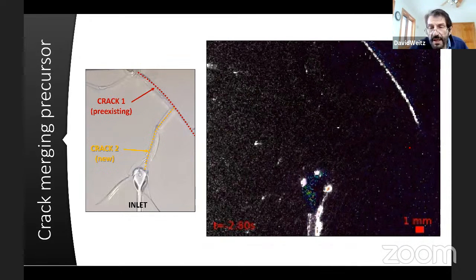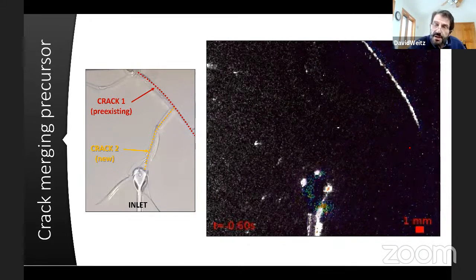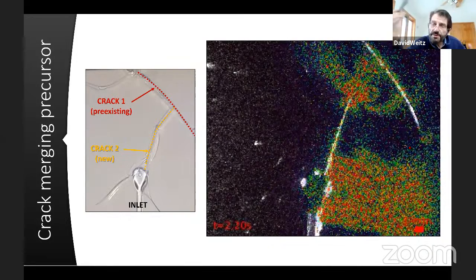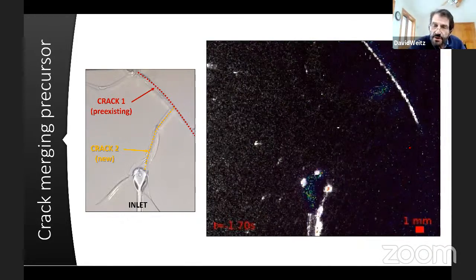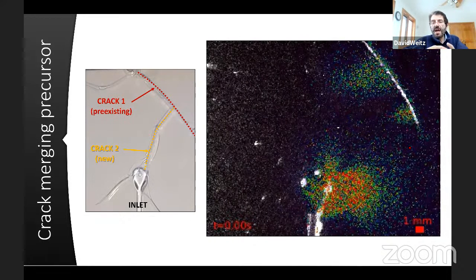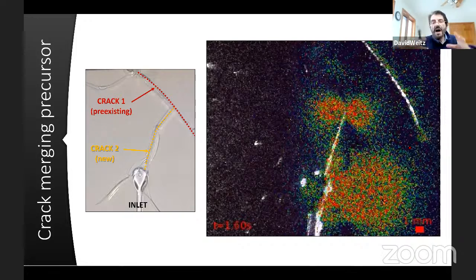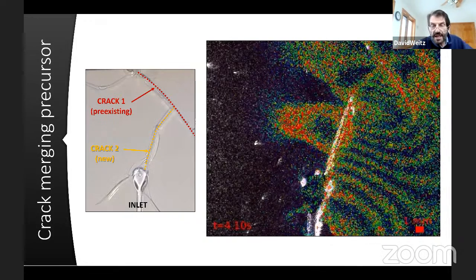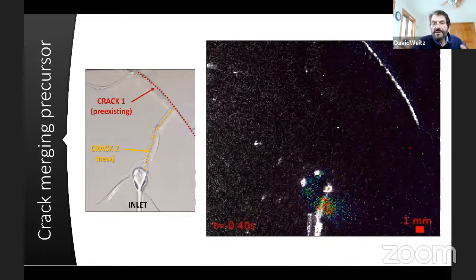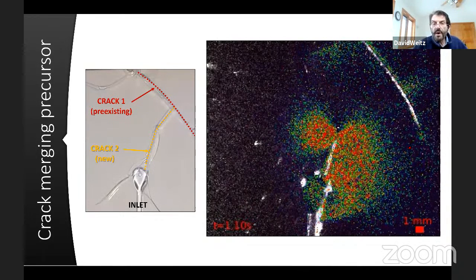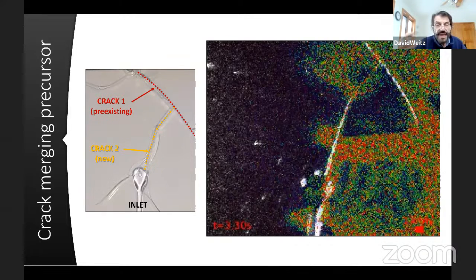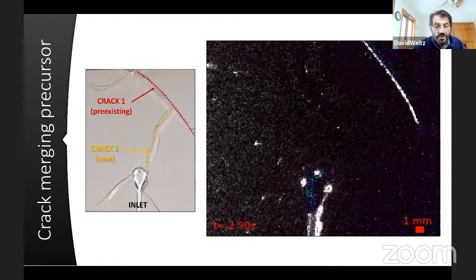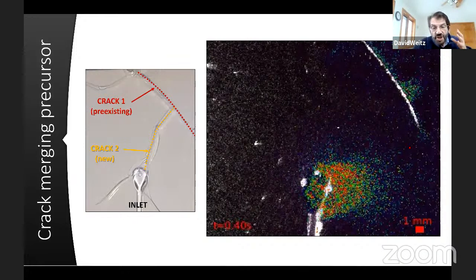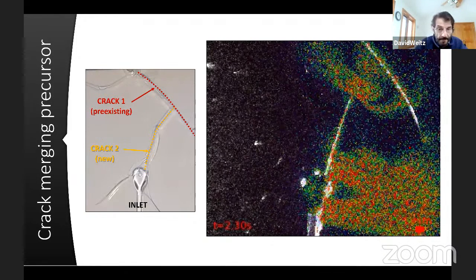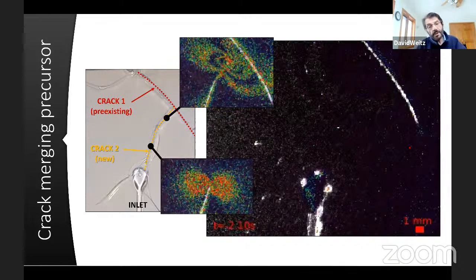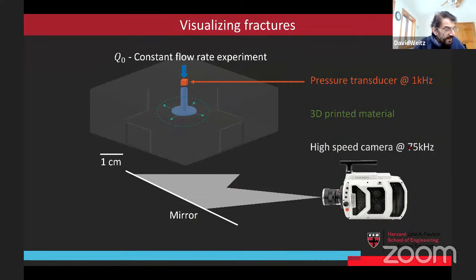This is a crack. And the important thing, and we saw why this is important, if we want to understand the interactions of the crack, we really do need to understand the motions, the strain fields of the solid far away. It's really a solid. We really want to understand the strains far, far away from where the tips of the cracks are moving. And that's what allows us to understand the interactions between the different types of cracks, the change in direction, really what's happening. And so here's just another example. Okay, so that's one thing that we've done.